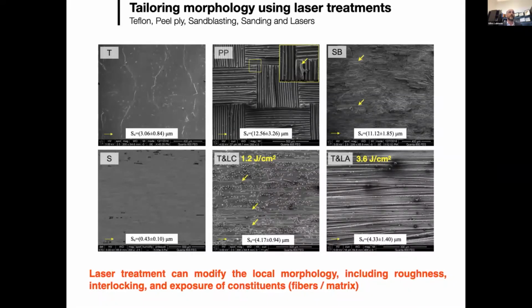this is typically a Teflon, a classical composite surface. This is when you are using peel ply, so you recognize the fabrics. This is when you are using sandblasting or sanding. When you are using laser, depending on the energy, the fluence of your laser, you can get completely different treatments. You can get a surface effect that only cleans the chemistry on the surface, so just surface cleaning. Or you can have a more ablation effect, which means you completely vaporize your resin, expose the fibers, and completely change the morphology.